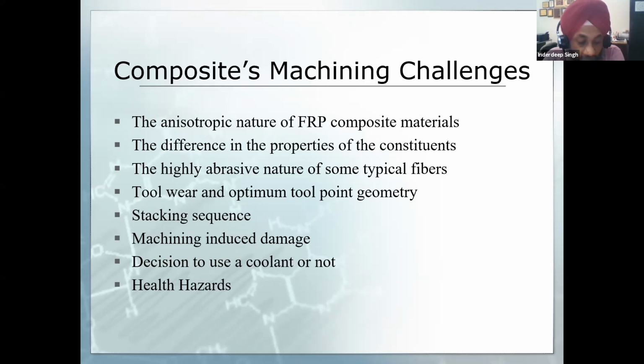Otherwise, I have myself seen that especially in glass fiber based composite materials, when I was doing my PhD, you cannot make more than 8 to 10 holes with a fresh high speed steel drill. So you are using an HSS drill for making holes in glass fiber based epoxy composite materials. The drill will wear out very fast. Maybe 8 to 10 holes can only be made, and then the drill will wear out.